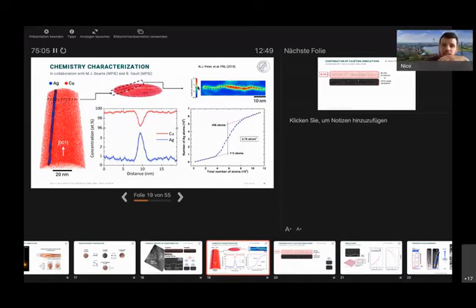So in these lateral dimensions, I would say there's always a local blurring and a little uncertainty about where atoms come from. To be very honest with you, I don't really know where this comes from, but there is not so much we can do about it. The good thing is we do observe the faceting, which is nice in atom probe. I would not have guessed to see it based on the dimension of the faceting. However, therefore, we do the highest structural resolution in TEM, where we do see exactly where something sits. So the APT is more or less the confirmation of the chemical species and how much we have. That we see the faceting as well is just a plus for us.